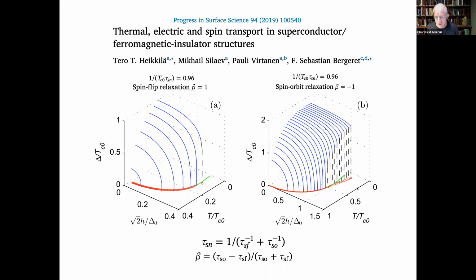Then you turn up the temperature by moving out this scale. And as you turn up the exchange, now it becomes second order. The red curve is where it hits the axis and superconductivity is destroyed. The gap goes to zero. But out here, it's first order, where the curve would actually be backbent as it was from that Sarma paper that I just showed, and that indicates the first order transition. As you turn up the exchange, that's the graph that I showed before. But you can also do a couple of other things.